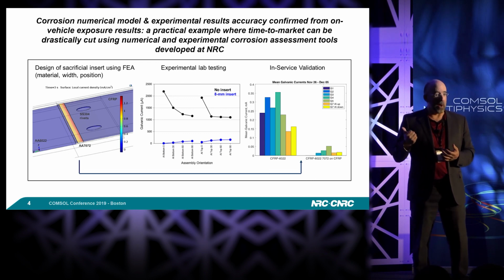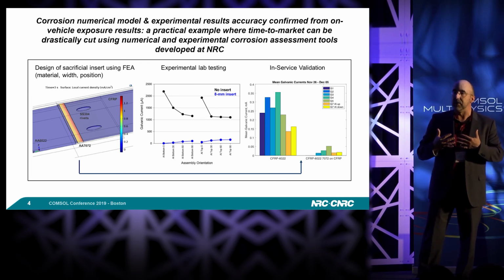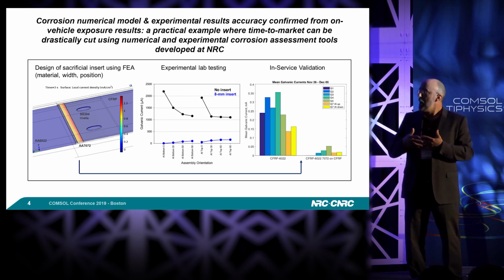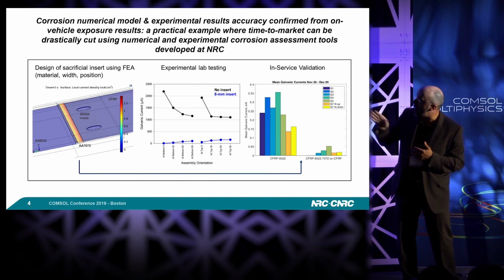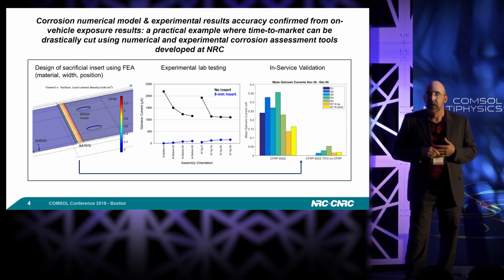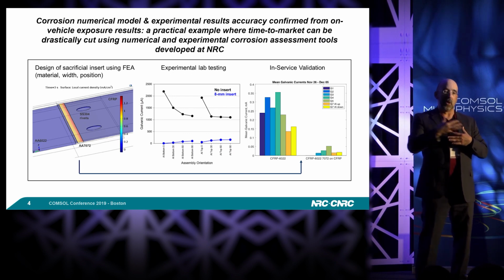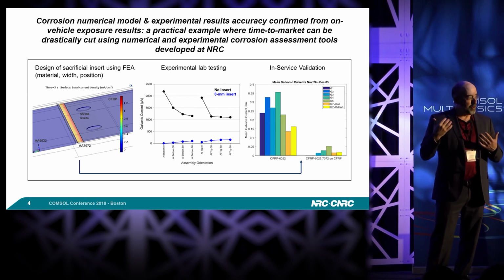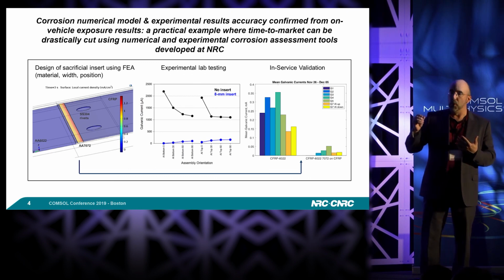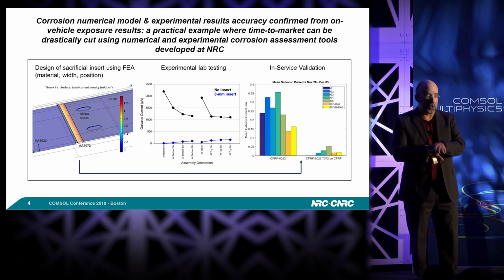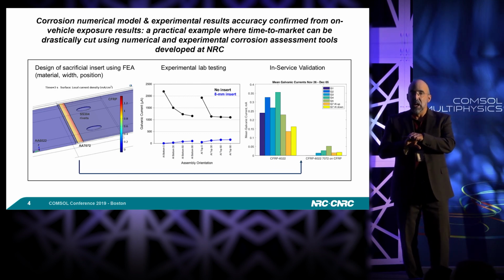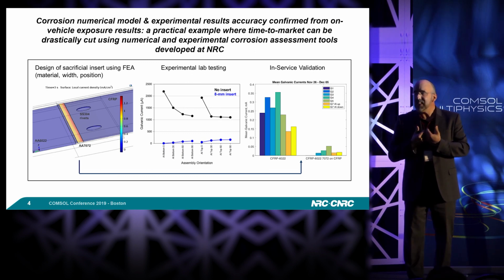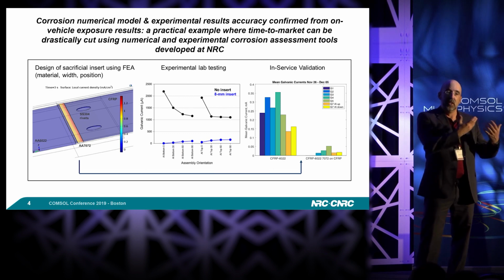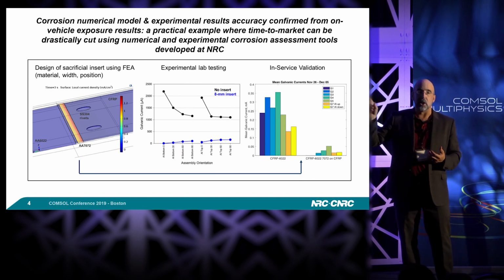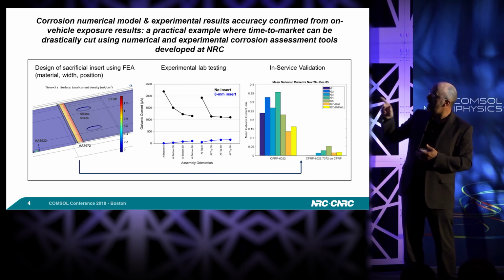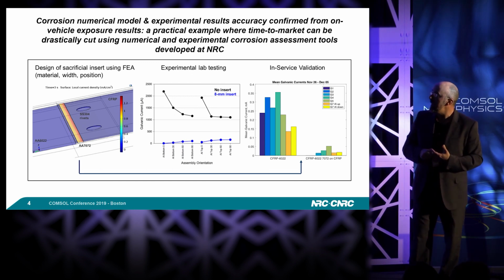Let's consider the simulation you have on the left. So we put two materials in contact. We have aluminum with carbon fiber. What is going to happen here if you don't have this bar in yellow-red? If you simply have aluminum with CFRP, CFRP will make the aluminum corrode. Now, what we've put is a sacrificial insert. We put it directly on the CFRP. It has no structural function. Its only function is to eat the anodic current instead of having the anodic current flowing on the structural aluminum material next to the CFRP. So here we protect the structural component with this sacrificial insert.